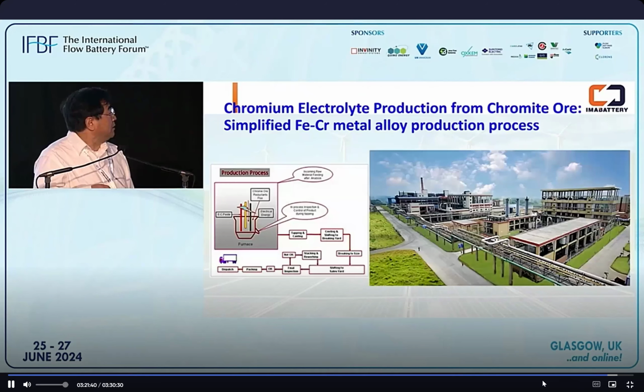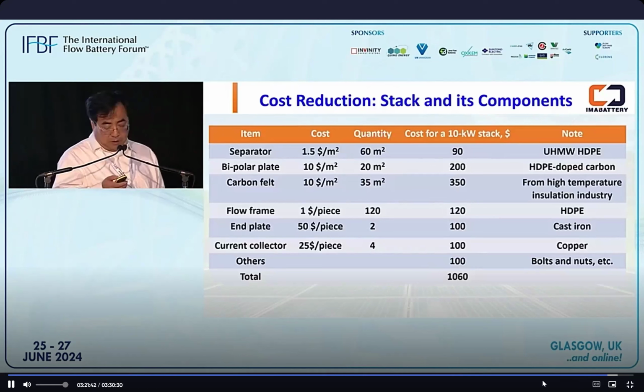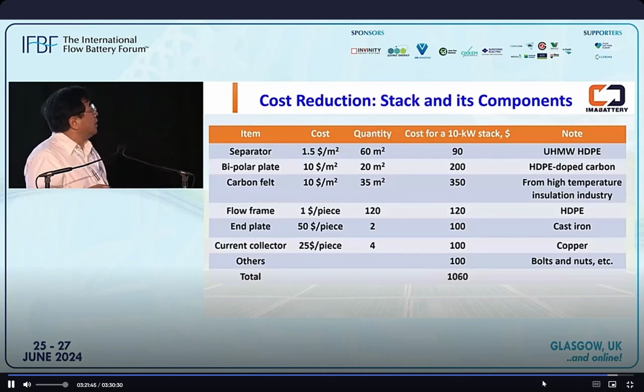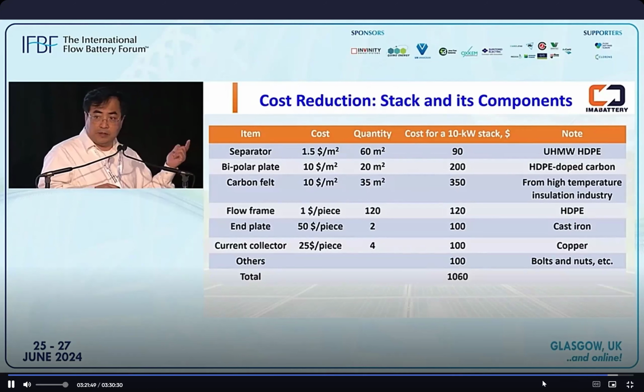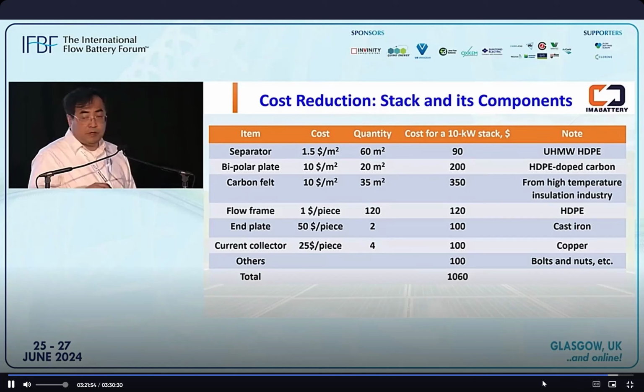So that's the electrolyte part, and then we are also working with many vendors on the stack part. The first thing, as I mentioned, we reduce the hydrogen concentration in the electrolyte. We can use an HDPE porous separator. We already identified suppliers at about $1.5 per square meter, and they have millions of square meters production capacity per year. Bipolar plate, $10 per square meter. Carbon felt, $10 per square meter.